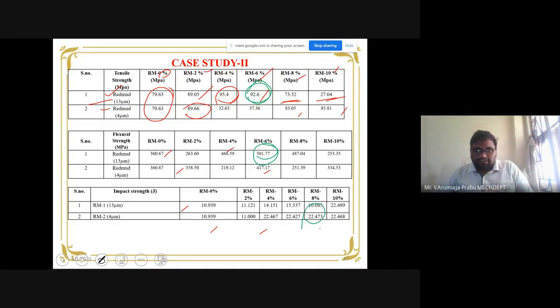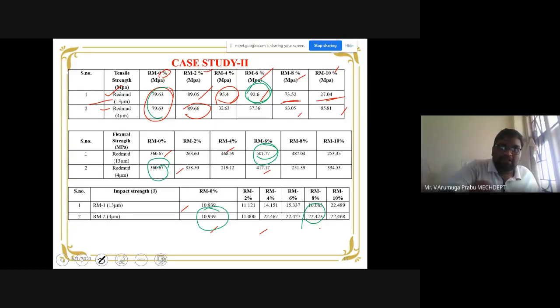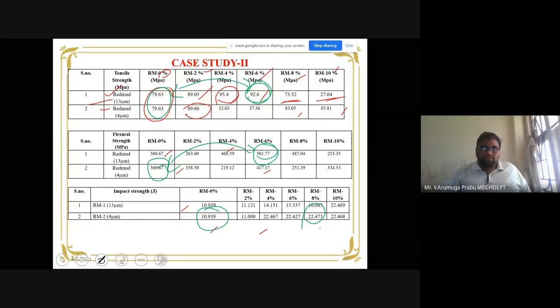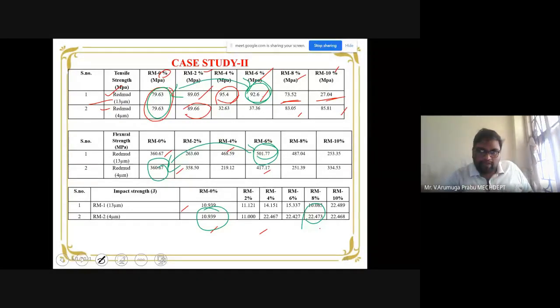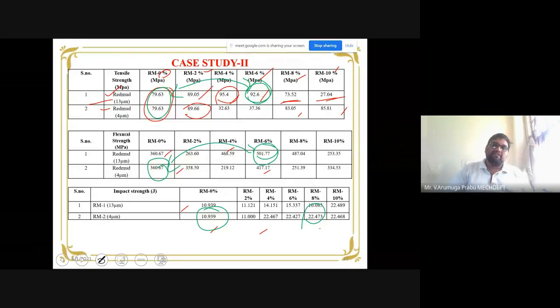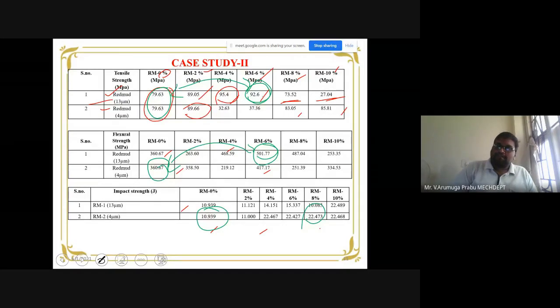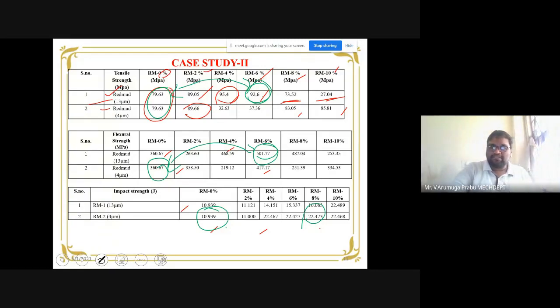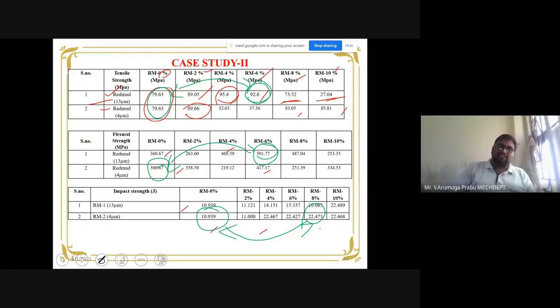So if you see, when compared to 0 in all cases, now compare the 0 in all cases. While comparing, it is going to produce a much better improvement in this strength. The 0% is only your fiber and matrix combination results. On the other hand, if we include the filler as a secondary reinforcement for producing the hybrid composites, the enhancement of strength is noticed in all the cases, that is, tensile, flexural and impact properties.